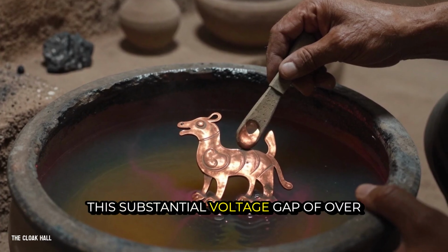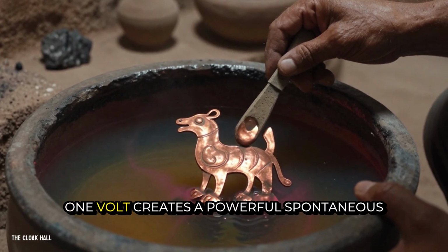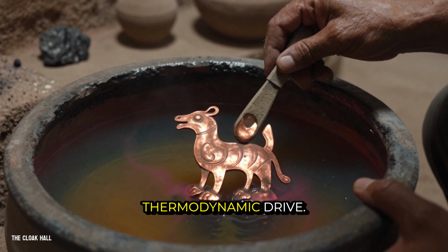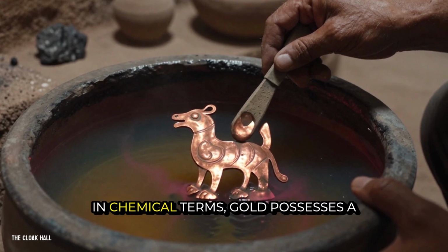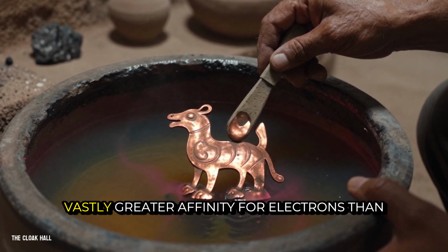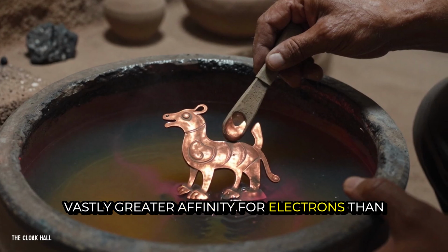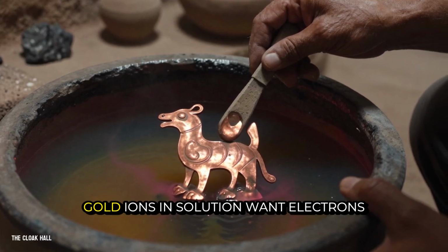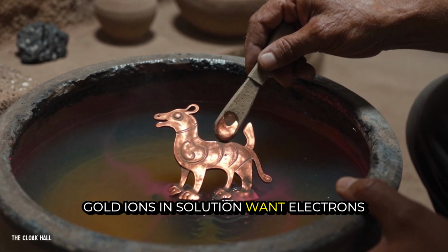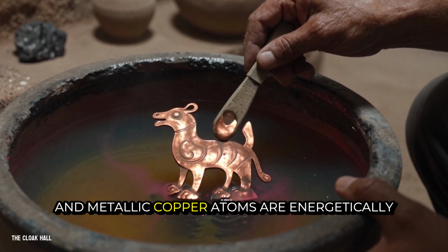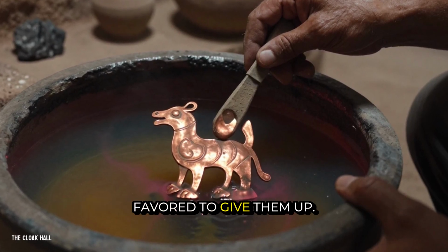This substantial voltage gap of over 1 volt creates a powerful, spontaneous thermodynamic drive. In chemical terms, gold possesses a vastly greater affinity for electrons than copper does. Gold ions in solution want electrons, and metallic copper atoms are energetically favored to give them up.